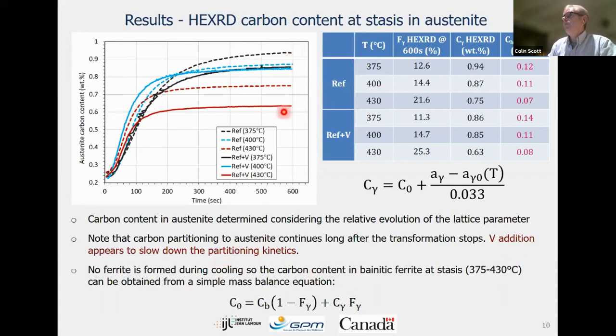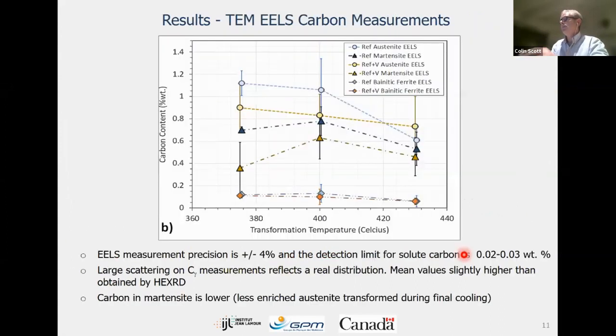Now, because we're not forming any ferrite during the cooling, we can calculate what the carbon content in bainitic ferrite has to be, assuming there's no precipitation, at stasis, just from a simple mass balance equation. And these are the numbers that you can see here. So what you can see is that quite a significant amount of carbon in the bainite, 0.1 or more. There doesn't seem to be any real difference between the two, reference or reference plus vanadium. And we have a decrease in the carbon content as the transformation temperature increases.